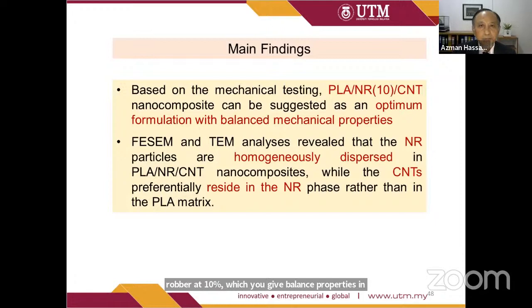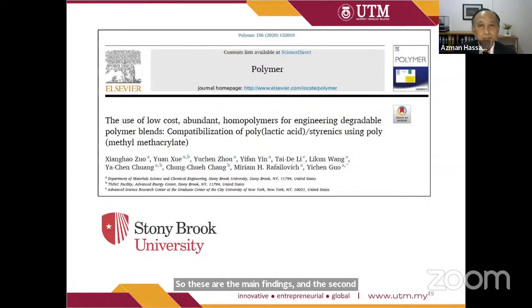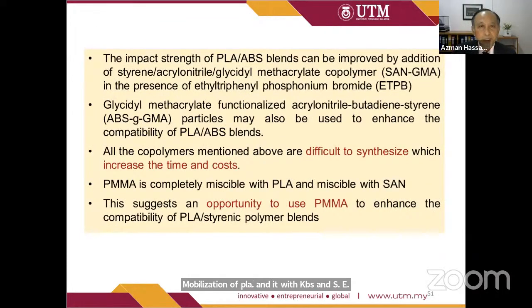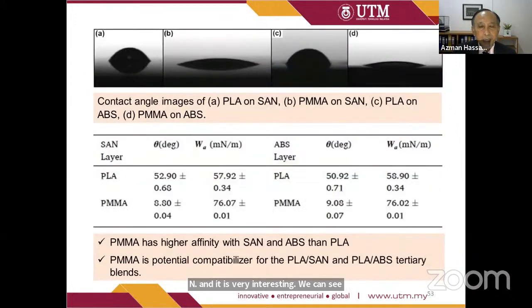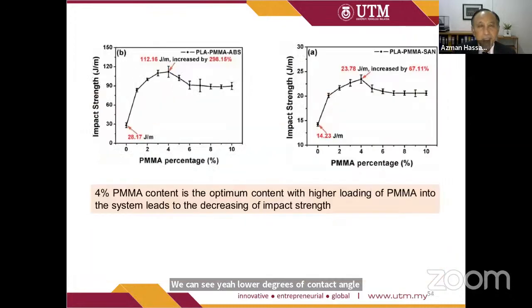So these are the main findings. And the second paper, which is very recent, is the use of polymethyl methacrylate to improve the compatibilization of PLA with ABS and SAN. And it is very interesting. We can see that the PLA has improved, and it has been supported by the contact angle measurement. We can see here the PMMA has lower degrees of contact angle compared to PLA and SAN, resulting in improvement of impact strength at addition of 4 weight percent PMMA content.